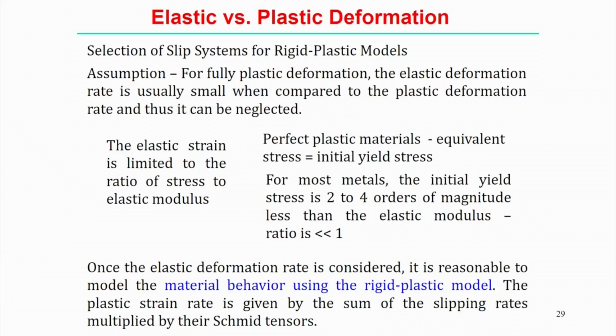A perfectly plastic material is one where the equivalent stress is basically equal to the initial yield stress. For most metals, the initial yield stress is 2 to 4 orders of magnitude less than the elastic modulus, so that ratio is very small as compared to 1. So, once the elastic deformation rate is considered, it is reasonable to model the material behavior using the rigid plastic model. The plastic strain rate is given by the sum of the slipping rates multiplied by the Schmid tensor.